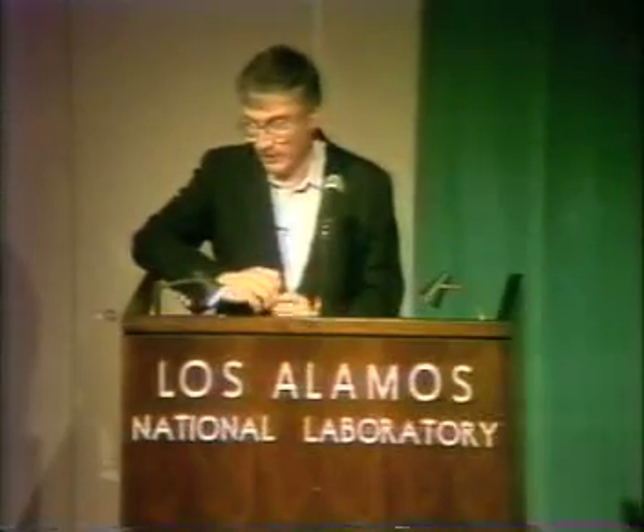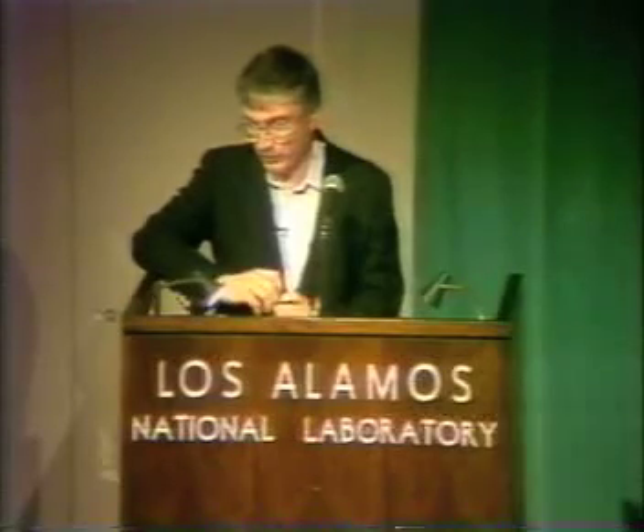I believe you made a comment that it's necessary to use palladium rods rather than, say, palladium foil. Well, no, the reason we went to rods was to have a convenient method for maximizing the volume to surface area ratio, so we could unambiguously say that this process is a function of the volume of the metal. In other words, it takes place inside the metal. We have used sheets. Sheets, indeed, will be a method for building a device, for instance, for heat production. But you can certainly use any geometry you want.